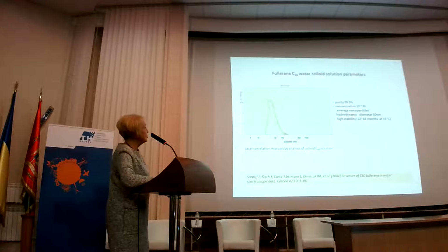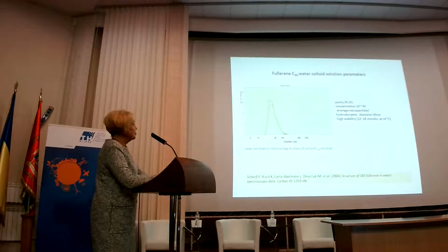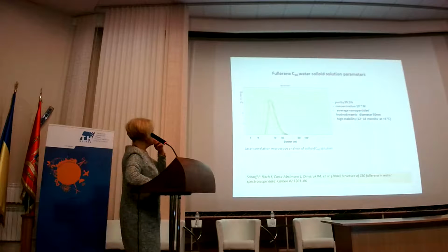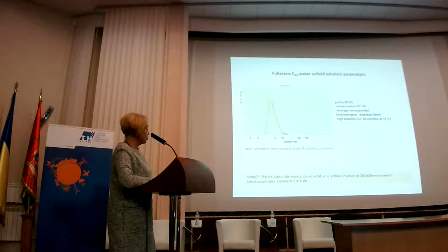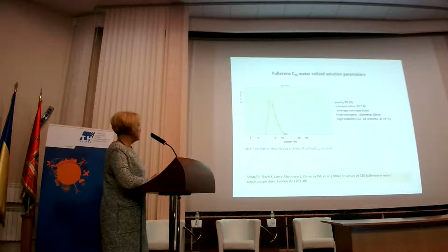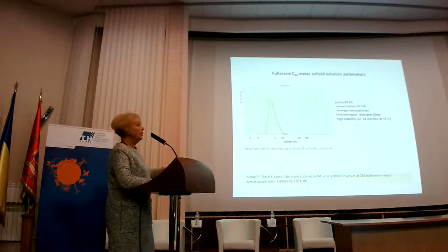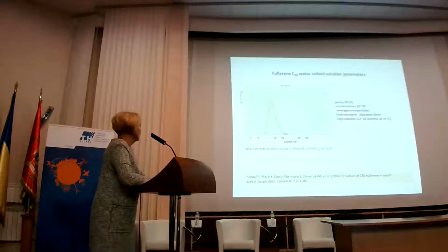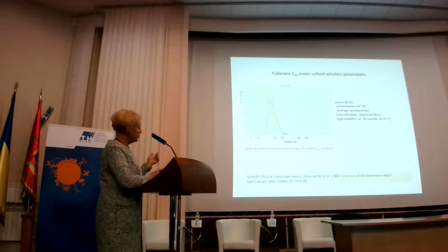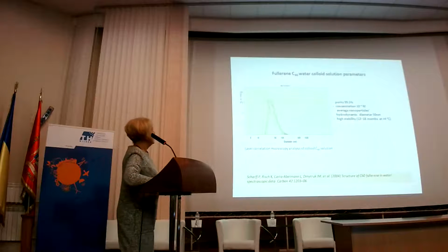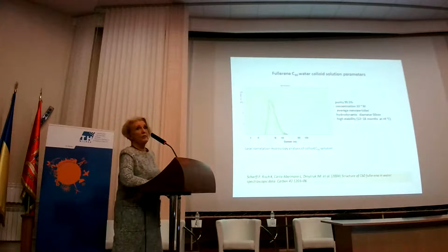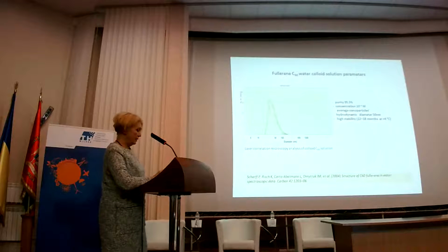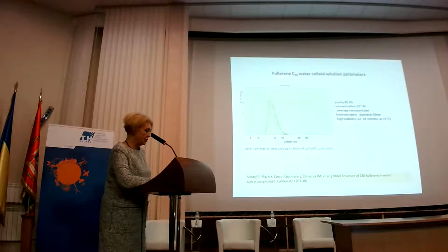of 10 to the minus 4 moles per liter, average nanoparticle diameter 50 nanometers, and by analysis with laser correlation spectroscopy, we have shown that this diameter was not changed in time during measurements. High stability also is very important. This water colloid solution was stable for more than 1 year at appropriate temperature storage.